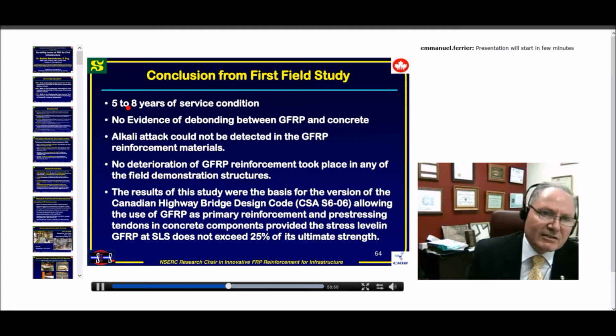At that time, the structures had 5 to 8 years of service condition. Of course, it's not too much, but it at least shows something, because I remember at that time in 2003, 2004, we looked at some papers done by researchers from lab testing, and they were showing that when GFRP is put in concrete, the degradation starts immediately. Even some of the papers, I remember, were published in the ACI Structural Journal. They were showing the service life could be 1 year, 2 years, 3 years, but that was from accelerated aging tests in the lab. Here it was 5 to 8 years without showing any degradation. So it was really very encouraging and very positive results.